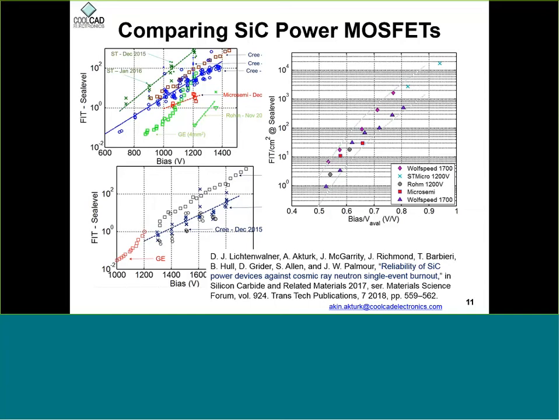On the right, I'll talk more about this later, but you can see that we measure different voltage rated parts and different parts from different vendors, but there's a way to collect that information onto one curve. We plotted this curve with Dan Lichtenwalner from Wolfspeed, and he did a great job. What we did was plot failure in time normalized by area versus applied bias normalized by the avalanche rating. So there's some trend irrespective of who makes these devices and what the voltage rating of these devices are. I'll talk more about this in the next few slides.